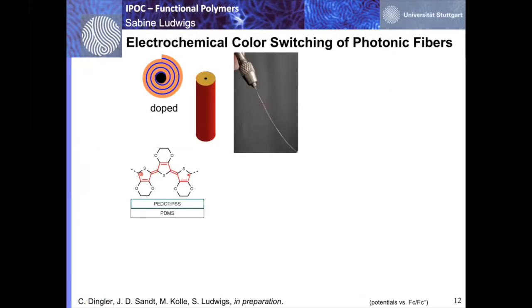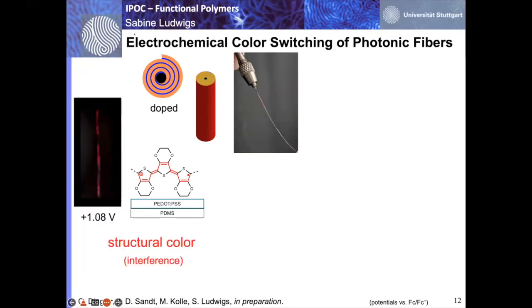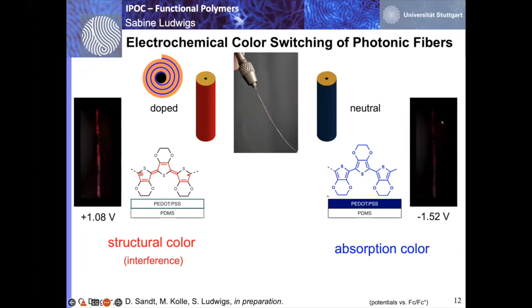Coming from classical electrochromism, we are currently preparing a paper with my colleague from MIT, Matthias Kolle, where we use bilayers of PEDOT:PSS and PDMS. PDMS was this elastomeric material, in very thin layers just a few tens of nanometers thick, and we roll them up on carbon nanotube fibers. And what we see is that these fibers have a certain color. My colleague Matthias Kolle is specialized in optics. This multi-layer cladding, this photonic fiber, appears red in the doped state, and it appears blue, and you can't see the color here anymore, at minus 1.52 volts. So if it's fully de-doped, then the color changes.